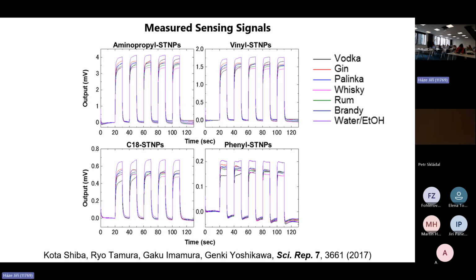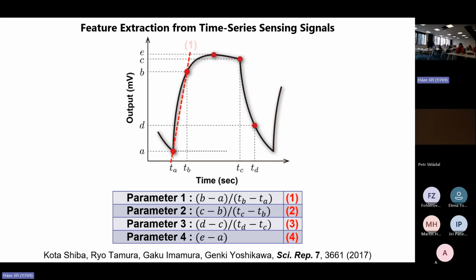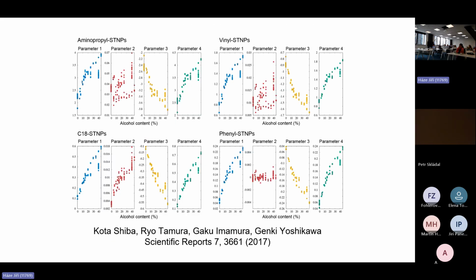In this case, these are all 40% liquors. So if we only focus on the signal intensity, it's kind of impossible to differentiate these. So we extracted these 4 features from our sensing signals and examined the relation between alcohol content and the parameters. This looks very random, so it's not a good feature, but these show a positive relation, a negative relation, and so on.